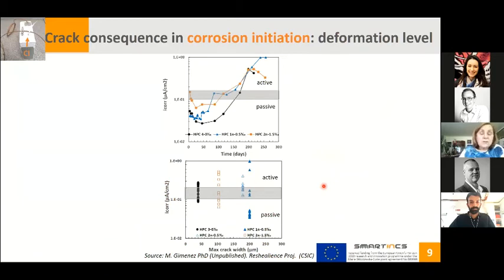Some results are shown here, from the PhD of Mercedes Gimenez within the Resilience project. Here we have considered a high performance concrete that has been previously exposed to a different deformation level, and we can observe that when exposed to chloride penetration the corrosion is initiated at different moments. This is the corrosion rate, and I have highlighted here when it is passive and when it is active. And we have noticed that with the different deformation levels, the corrosion is initiated